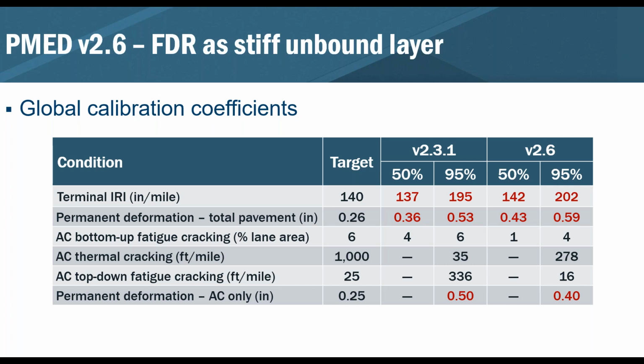So again, for version 2.3, I put both the 50% reliability and 95% reliability for 2.3 and for 2.6, and you can see that here. Since there is no reflective cracking in the unbound layer, you don't see that here. I also am only showing information on the 50% for the 3 criteria that I used on those graphs that I just showed: IRI, permanent deformation, and bottom-up fatigue cracking. I'm showing those for reference, since I really don't have a sense of the thermal cracking or the top-down cracking from any of the results I got from Virginia on the in situ pavement performance.